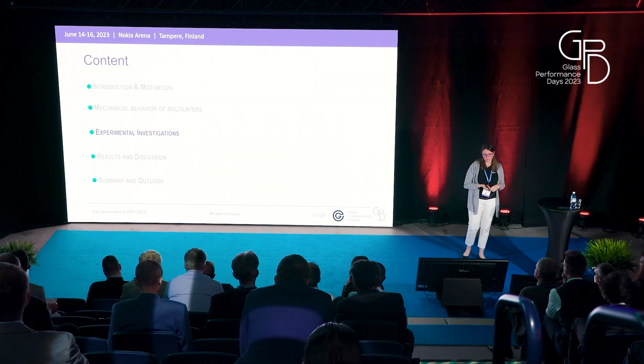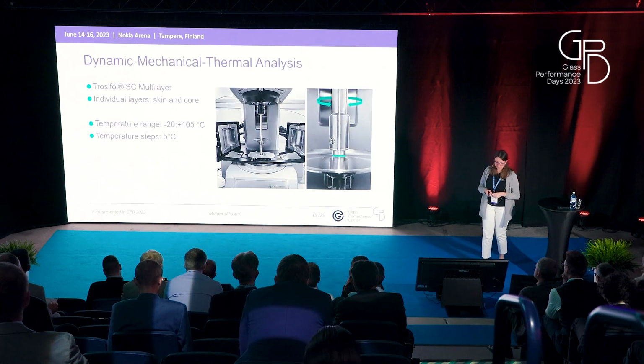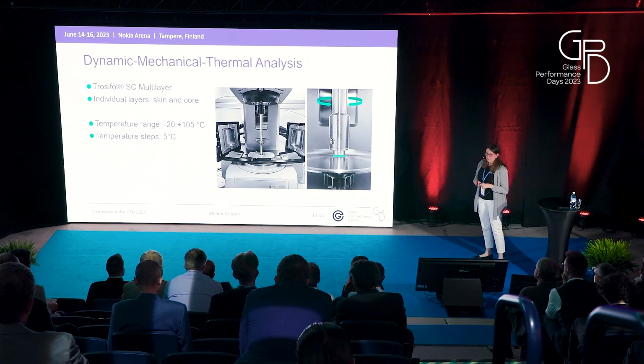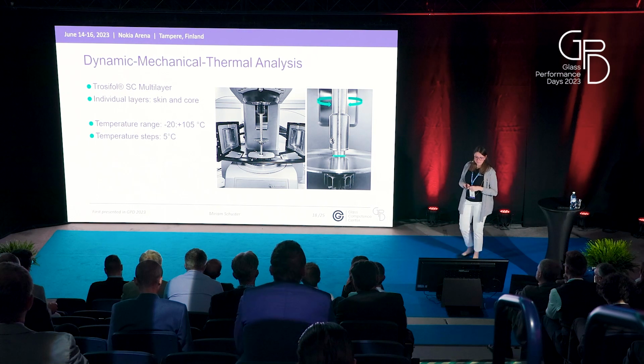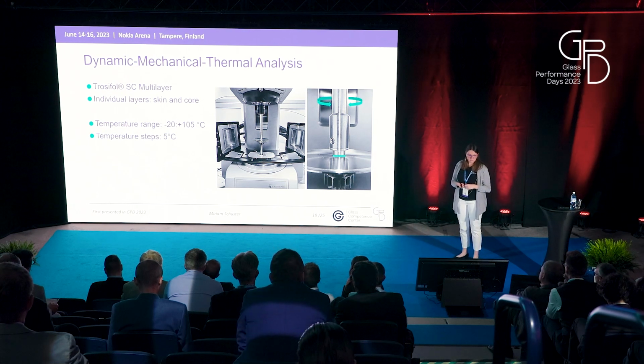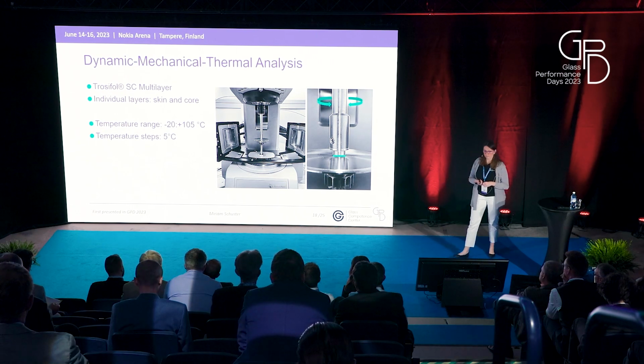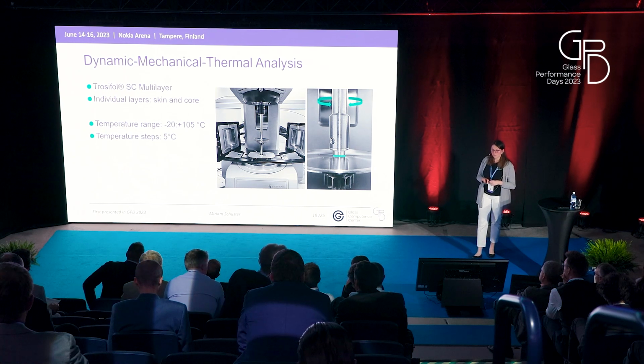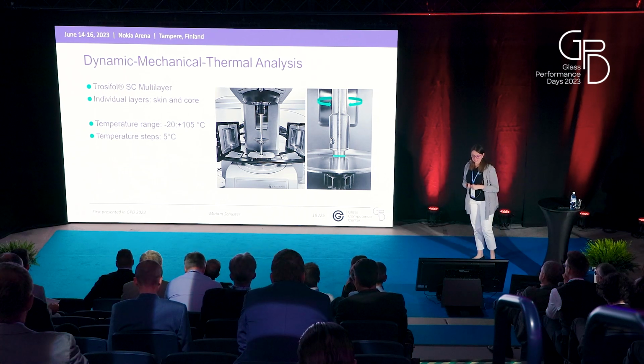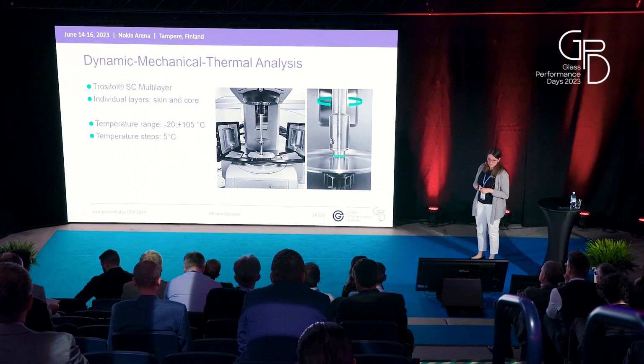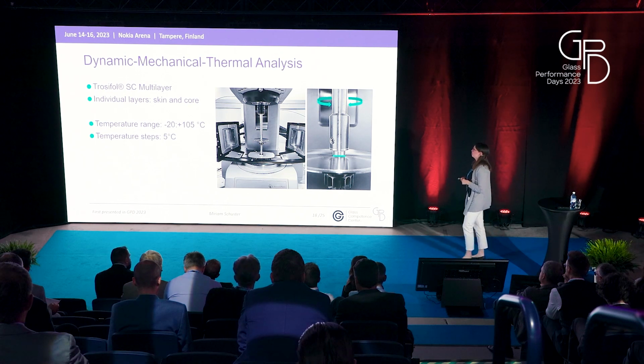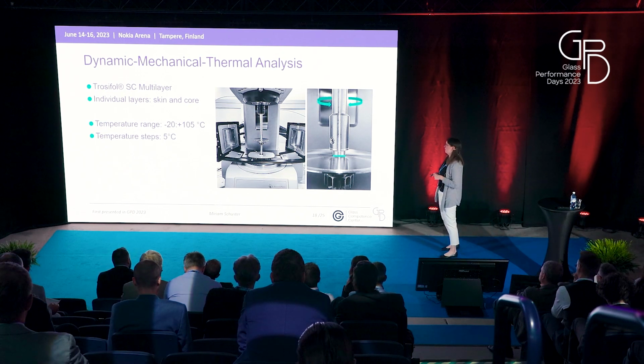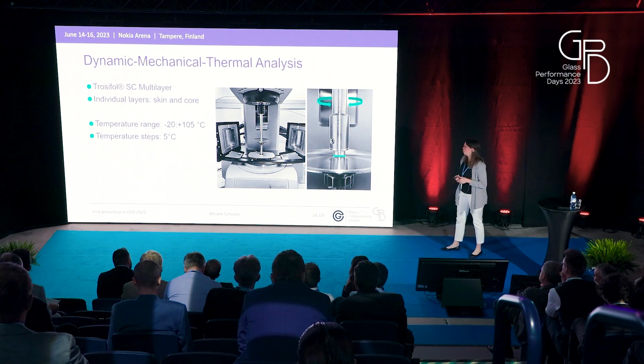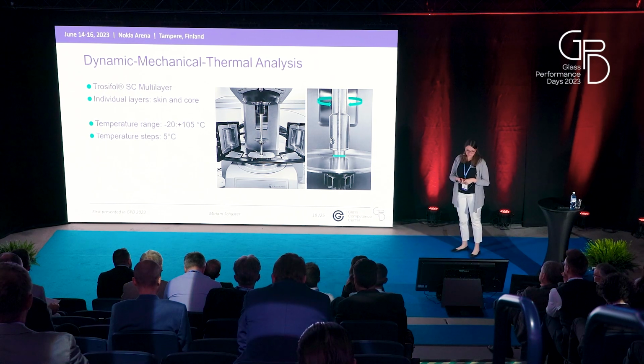Okay, let's come to the experimental investigations. So first, we did some DMTA tests. We did them on a trilayer from Kuraray, Trosifol as the multilayer. And we also did the tests on the individual layers. And we investigated temperatures between -20 and +105 degrees Celsius. And the temperature steps were 5 degrees Celsius.